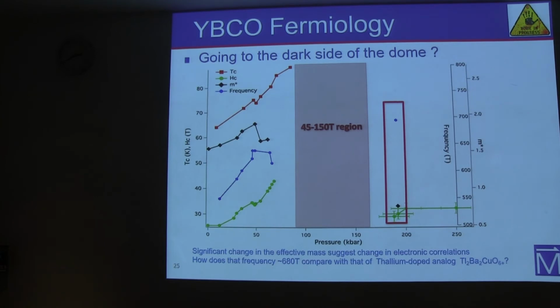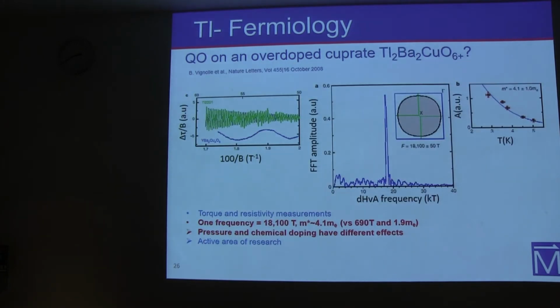So how does that compare with the initial picture that I showed you earlier with the large Fermi surface that was obtained with the thallium doped cuprate? Those are the results obtained by different groups on that compound by doing either torque or transport measurements. And basically what they get is one frequency of the order of 18 kilotesla, and effective masses of the order of 4.1 electron mass. So this is completely different from our result of 700 Tesla.